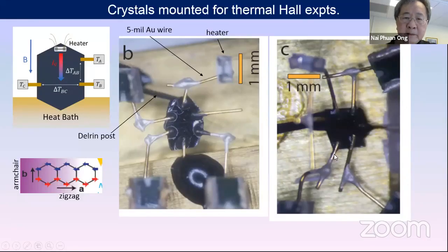Okay, so the crystals grown. All right, ruthenium chloride actually is a very finicky material. It's layered and it's highly sensitive to strain, right? If you abuse the crystal too much by flexing it, the dislocations introduced will broaden out the antiferromagnetic transition and introduce spurious effects that are not observed in the pristine crystal. So these are fairly large crystals of the size of millimeter or more, provided by the Oak Ridge group.